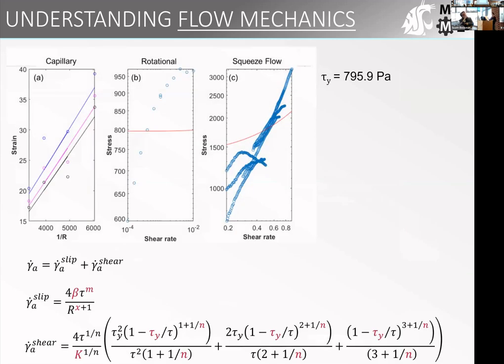Yeah, and so when we collect all of this data, we then put all of it into a model. We do basically a global minimization model to extract the shear flow and wall slip components. And when we fit our data to these models, we can extract these fit parameters related to wall slip and shear flow and calculate the slip and shear components of the apparent strain rate during extrusion.